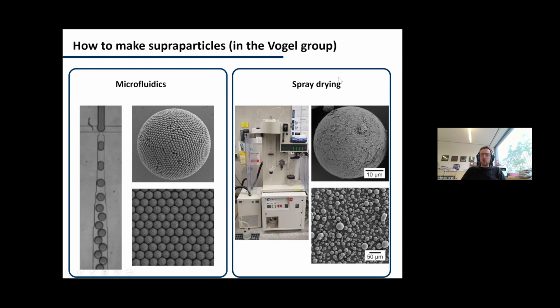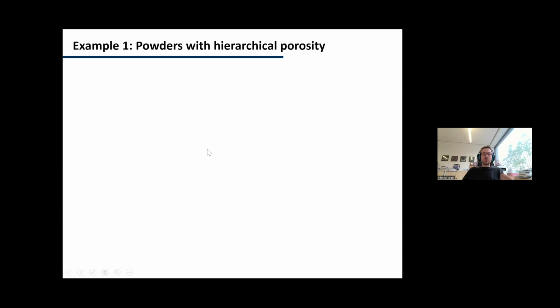And here on the other side of the world, you have spray drying, which I'm sure all of you know is just a very bulk or very large volume type of processing. So what you do is you vaporize a dispersion here at the nozzle, and then it dries out, you collect it here, and then you create particles that actually do not look very different from the microfluidics, but in the distribution of particle sizes that you obtain, of course, there's big differences. And because the time scale that you need for consolidation is very different, there's also some different physics at play that we can either leverage to our advantage or that we need to overcome in terms of ordering and so on.